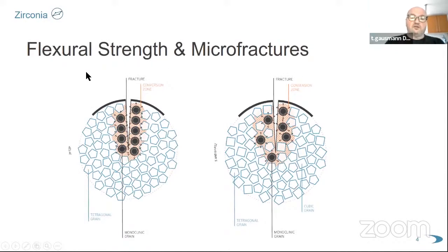Now we come to a point that is really important in zirconia. It's the phase change of zirconia when a force is put on the material. So you've got here in the left picture a fracture coming from above into the material, and you've got all tetragonal grain in this material. It would be like a normal 3 yttria material, like we've got shaded. It's a 1200 megapascal standard material. Whenever the force hits one of these tetragonal crystals, it is changed to monoclinic. When this crystal is changed from tetragonal to monoclinic, it will add volume to it. So it's getting bigger. You can imagine, this is only a sketch, when the force is inflicted on many of these tetragonal crystals, you will have a lot more volume added.